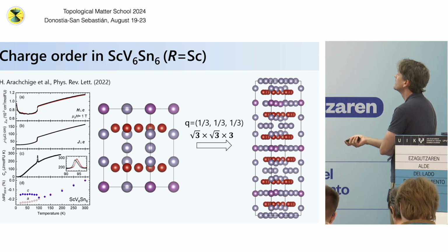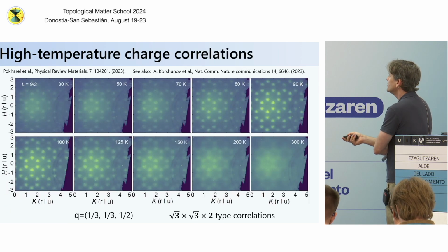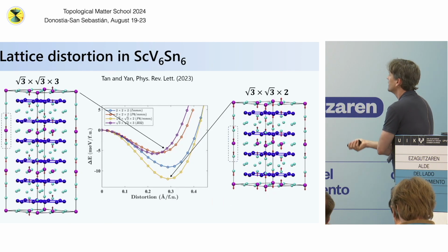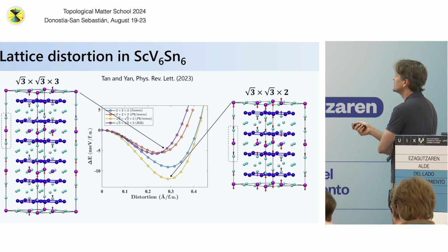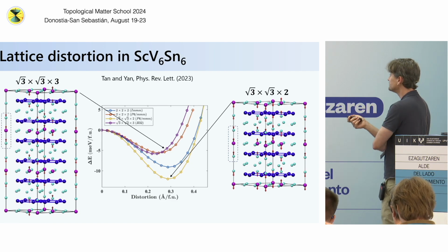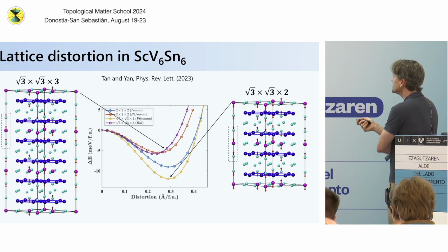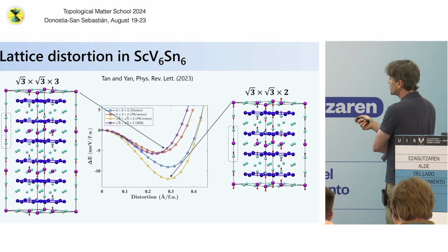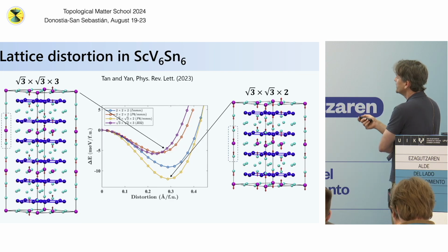And so it turns out in these compounds, if you look at DFT, which is just looking at the energy of stable structural distortions of the system, this is from Binghai Yan's group. It turns out there's a reasonably shallow energy minimum with a lot of different charge density wave patterns or charge order patterns that are predicted within a fairly close energy spacing of each other.